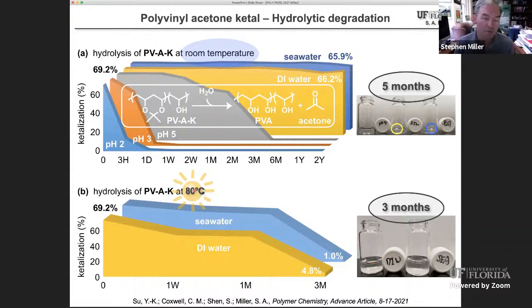So if they're in the ocean, certainly in a warm ocean for a long period of time, these polymers should in fact essentially disappear, and then hopefully biodegrade once you get to the polyvinyl alcohol stage because of its water solubility. Now, what does it mean to degrade at 80 degrees in 3 months? I'm not sure, but you can do some very gross calculations by understanding the kinds of barriers that are present. And I estimated in this paper, it was about 16 years, plus or minus a decade, in order for a polymer like this to degrade in the ocean, maybe a warm ocean. It's going to be slower in a cold ocean. But in a warm ocean, you might end up expecting these things maybe to degrade in 2 decades. That's a lot better than polyethylene and polypropylene, which probably will last 500,000 years, very long period of time in the open ocean.